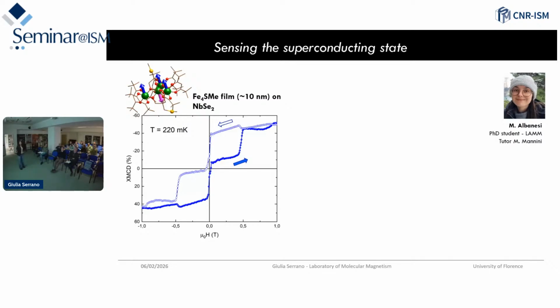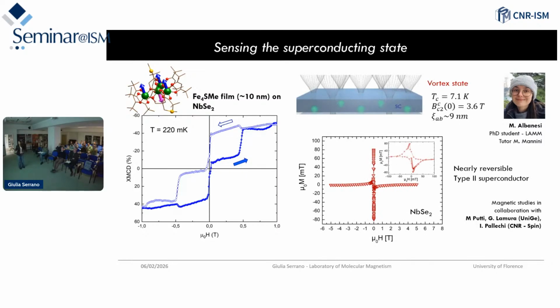Here we had a thick film, but quite ordered, of iron 4 single molecule magnet, the same molecules that I mentioned before. And we are on a niobium diselenide type 2 superconductor, in which we have the vortex state below 7 K. These measurements again are done in the millikelvin regime, and the BC2, the second critical field, the appearing of the vortex state, is at 3.6 Tesla. So in all this regime, under the molecule, we have the vortex lattice appearing.